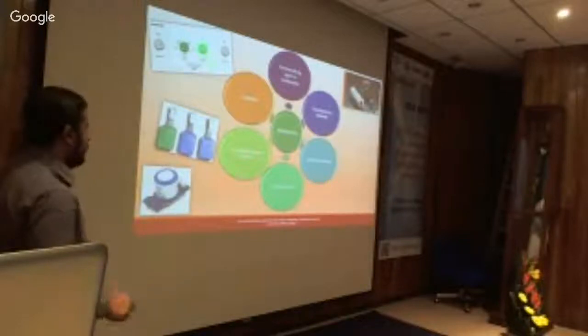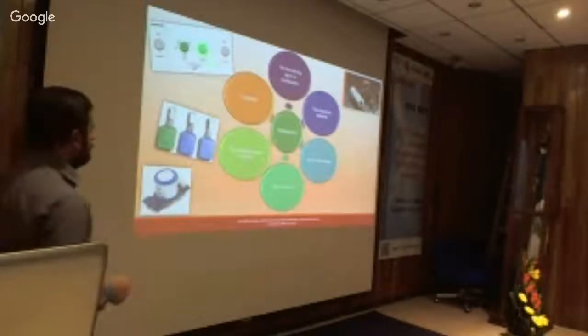The main applications of hydroxyapatite: it is used as a remineralizing agent in toothpaste and as a fluorescence material. It is used as an ionic conductor and especially in gas sensors due to the defect of the OH, which is the hydroxy part. And it is a thermoluminescent material. Around 180 degrees centigrade, it has luminescence properties. Generally, it is also used as a catalyst and in many biomedical applications.